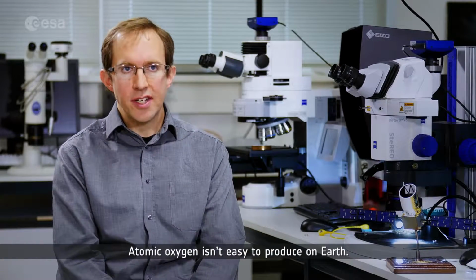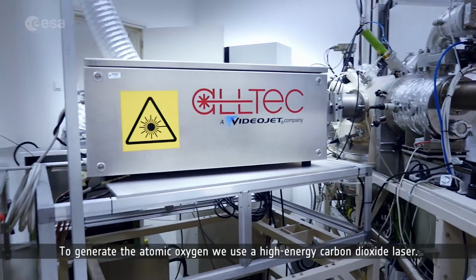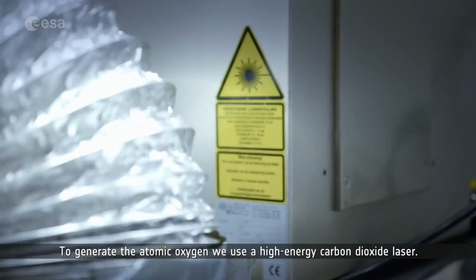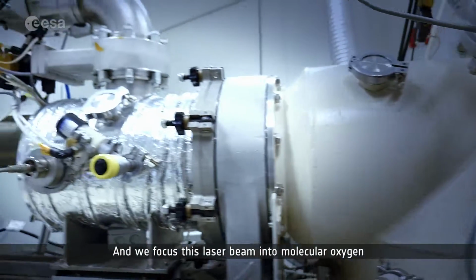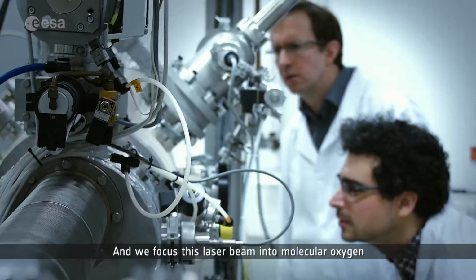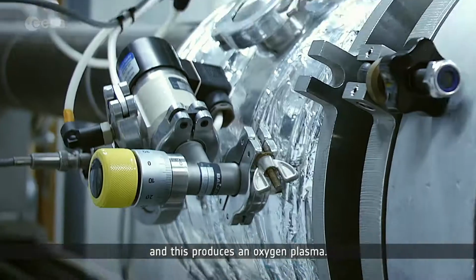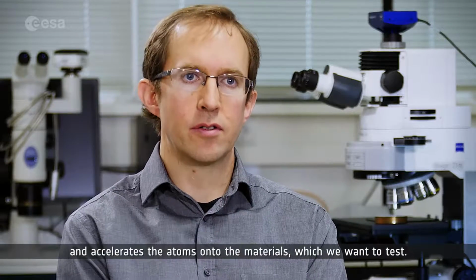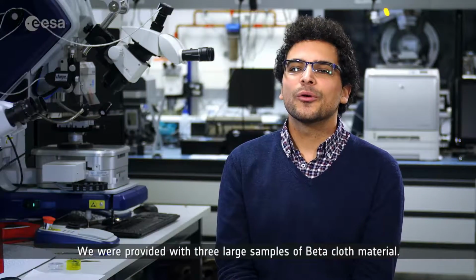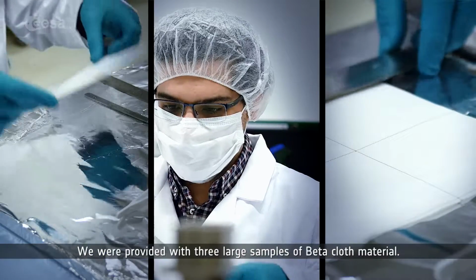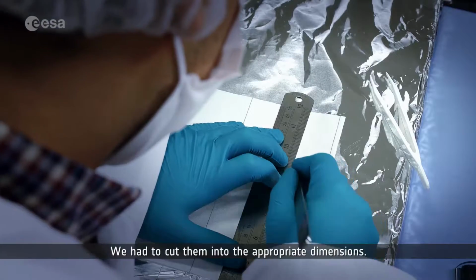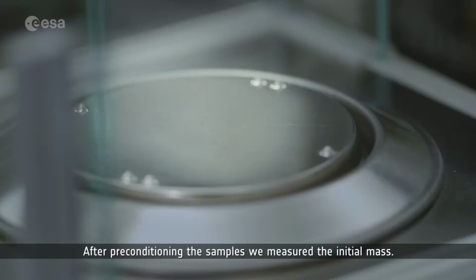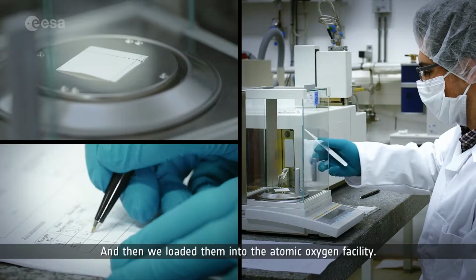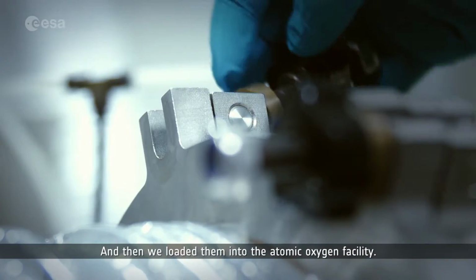Atomic oxygen isn't easy to produce on Earth. To generate the atomic oxygen, we use a high-energy carbon dioxide laser, and we focus this laser beam into molecular oxygen, and this produces an oxygen plasma. The oxygen plasma then expands into a vacuum chamber and accelerates the atoms onto the materials which we want to test. We were provided with 3 large samples of beta cloth material. We had to cut them into the appropriate dimensions. After preconditioning the samples, we measured the initial mass, and then we loaded them into the atomic oxygen facility.